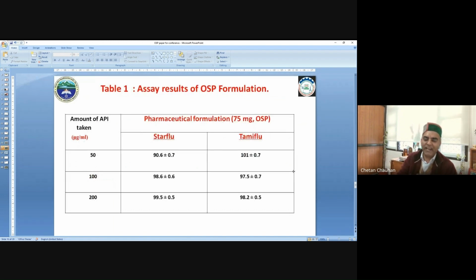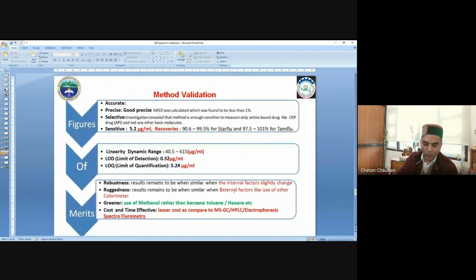So when we apply the same standardized conditions to the formulations, we have taken different amounts of the drug, like 50, 100 and 200 microgram per milliliter, and we apply them to different formulations like Star Flu and Tamiflu. We obtain a very good recovery with good standard deviation results. So we have validated on these lines. We find that the method is accurate, it has good precision, and it is selective. Even a small amount of the substance can be analyzed by this method.